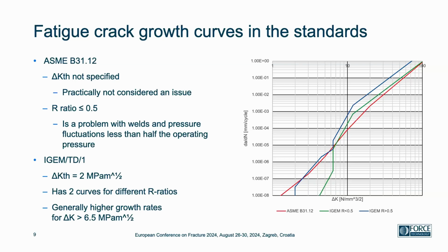But another problem is that the R ratio is for less than a half. So this might give some problems when you are assessing wells, or if the pressure fluctuations are less than half the operating pressure, because then the R ratio is above 0.5, and this curve is actually not applicable.